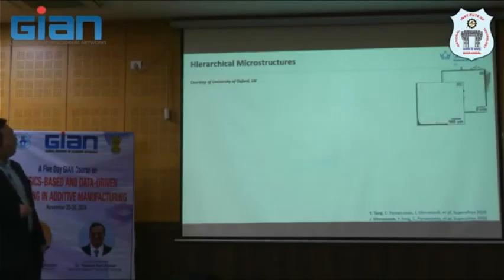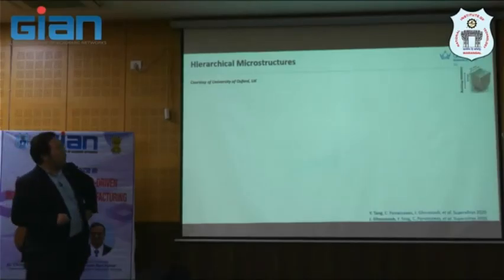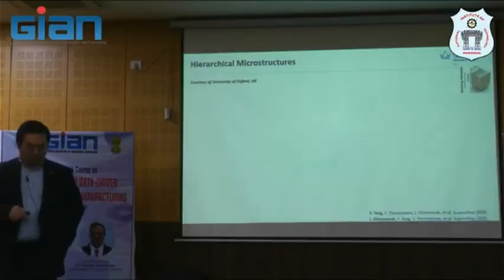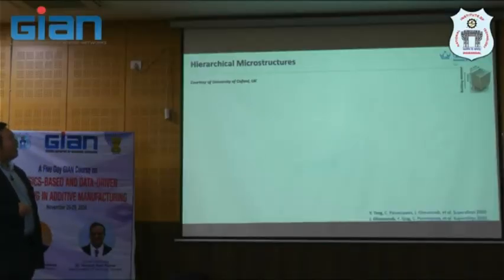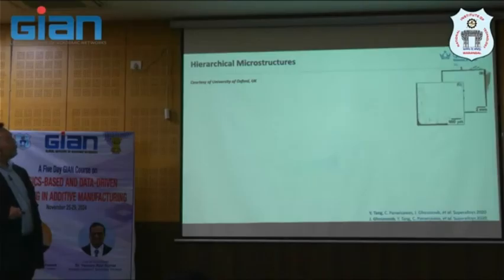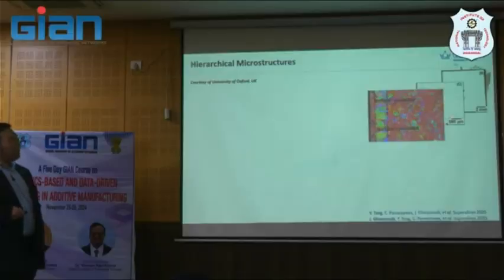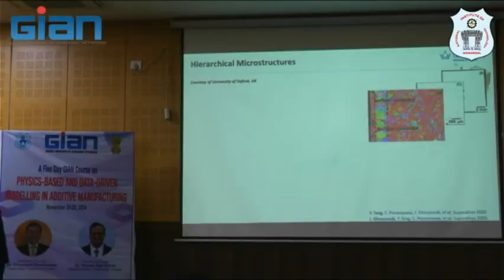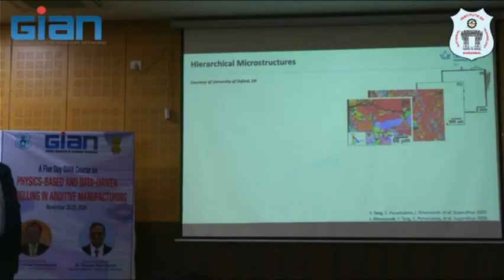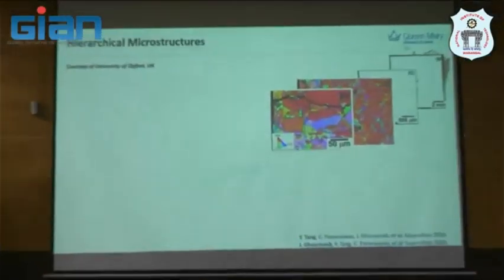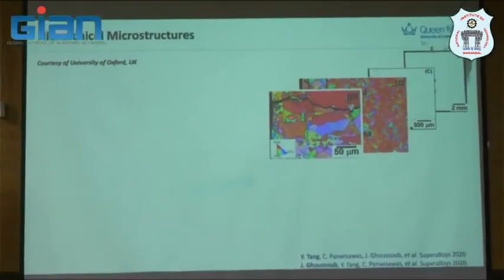Just want to show here how hierarchical it is. You see we have one 10 by 10 by 10. So just follow my slide. Clearly the next one, we map across this 10 by 10 by 10. And then we zoom into the corner of the 10 by 10 by 10. So this is just half a millimeter. And then we map the EBSD at this particular section in that corner. You will see this is surface connected, and then this is columnar grains, as I mentioned before, the bulk. And then when you zoom in a little bit in the columnar grain zone, which is mostly the zone where you found a lot of cracks at the edge, right? And this is something you can see.